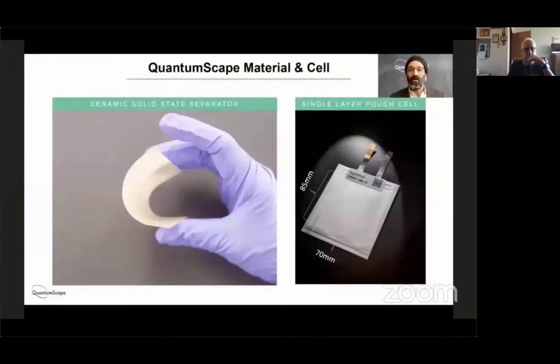So we have made a material, which is a solid-state separator. It's a ceramic material. It's shown in this image here on the left. As you can see, unlike traditional ceramics, this material is actually quite flexible. And we then take this material and make it into a single-layer pouch cell, as shown on the right. This cell has one cathode in it, one solid-state separator layer, and one in-situ formed lithium metal anode, and encapsulates all of the chemistry of the system in that pouch cell.